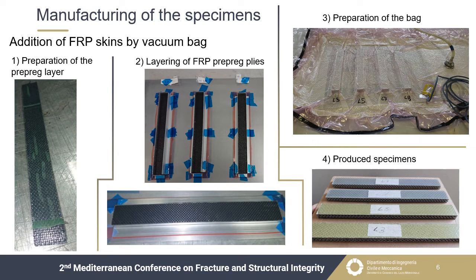Then further steps were required to create the composite skin. For this purpose, the prepreg vacuum bag process was chosen. FRP prepreg plies were prepared and layered on the mold, together with the lattice core. The number of prepreg plies was chosen in order to obtain a thickness of about 1 mm for all the face sheets. So 5 plies were necessary for carbon skins, 4 for aramid ones, and 9 plies for glass ones. This similarity was important to perform a meaningful comparison between the different types of specimens.